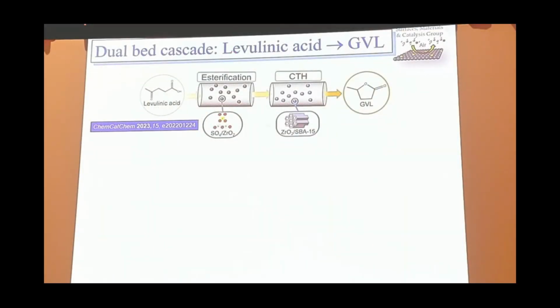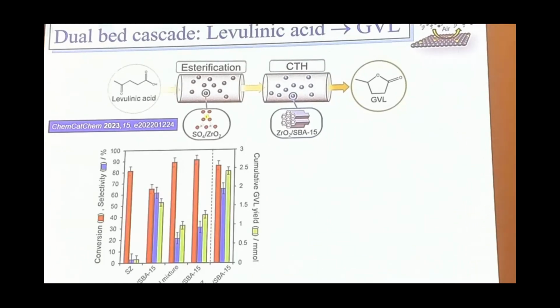And what we've done, again looking at flow reactions, is think about whether we can do a dual bed flow cascade. So in this case, we'll take the best catalyst that we've just made, the sulfated zirconia for doing esterification, and we will put that in front of the catalyst we used for the previous system for catalyzing the hydrogenation, and see how, with this dual bed, we optimize esterification and then optimize the transfer hydrogenation to GVL. And what you see is it does actually work.